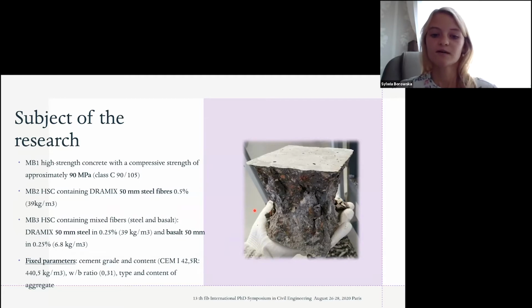Three types of samples were made. MB1, high-strength concrete without fibers, MB2, high-strength concrete with 50 millimeters long steel fibers in amount of 0.5%, and MB3, high-strength concrete with 50 millimeters long steel fibers and 50 millimeters long basalt fibers, 0.25% each.